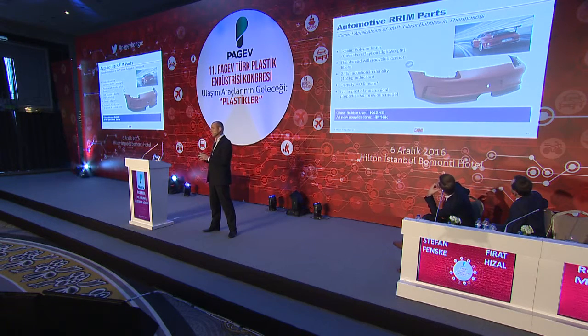This is also quite a recent one, introduced in the first quarter of this year. The rear bumper of this Porsche model is using glass bubbles now. They already had a lightweight bumper previously, but they still managed to reduce the weight of this bumper by 23% by using glass bubble material. So a very good achievement, because the density is now for the first time below 1. It's 0.9, which is quite an achievement. And they're going to replicate it over other models as well within that company.